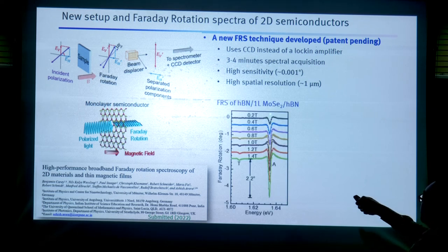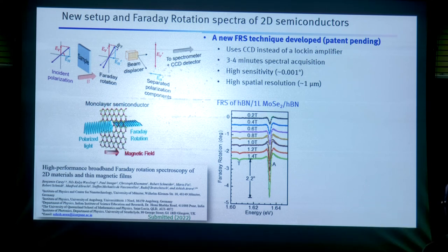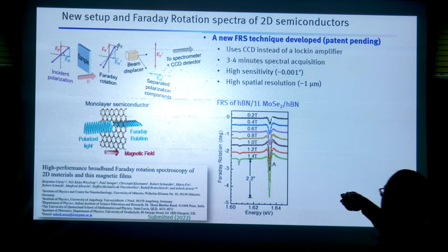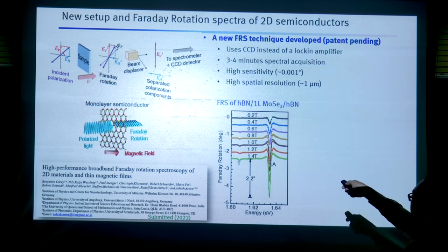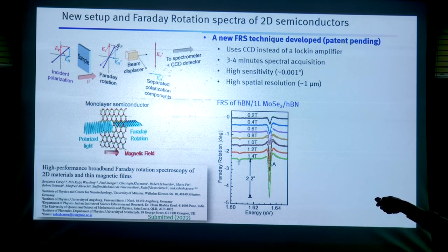If we measure the Zeeman effect just using Faraday rotation, because when there is Faraday rotation, there is Zeeman effect, or when there is Zeeman effect, there is Faraday rotation. I should have said it the other way. So there is Zeeman effect of excitons, and we are able to see this Zeeman effect just by increasing the magnetic field. Now, here I am seeing this Zeeman effect very nicely, a very clear signal, just at 0.2 Tesla.